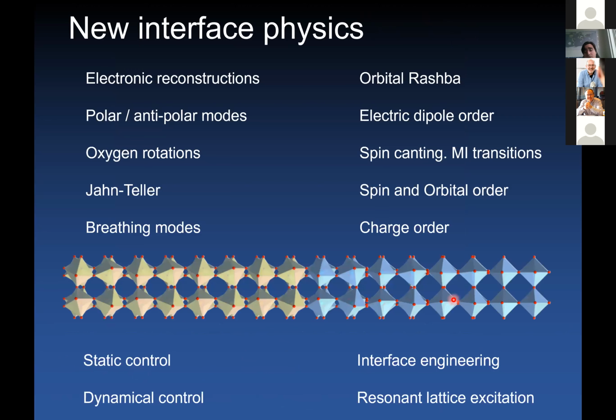Okay, and when you now create interfaces between materials that have all these symmetry lowering properties, then you have the problem of realizing a connectivity between the oxygen networks. So here I'm depicting a simple schematic case of a tetragonal or cubic system that meets a more distorted perovskite system. And as you can see at the interface, you need to resolve the connectivity of the oxygen network. One possibility is to create a leaking of distortions between the two materials. So here you immediately see that the interfacial region where these two materials meet is strongly structurally reconstructed.